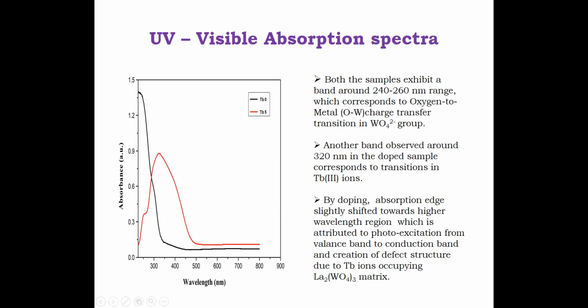That is shown here. Both the samples exhibit a broad band around 240 to 260 nanometer range, which corresponds to the oxygen to tungsten charge transfer transition in WO4 2-. Another band around 320 nanometers observed in the doped sample corresponds to the transition in terbium ions. And the absorption edge of the doped sample is slightly shifted towards the higher wavelength region, which is attributed to the photoexcitation from valence band to the conduction band, and also the creation of defect structure due to the terbium ions occupying the lanthanum tungstate matrix.